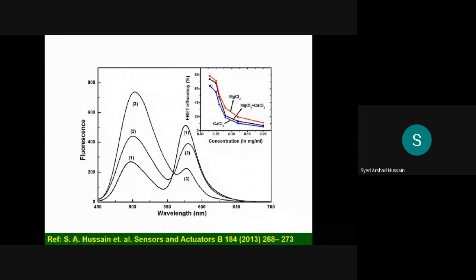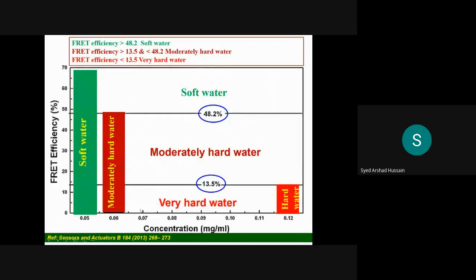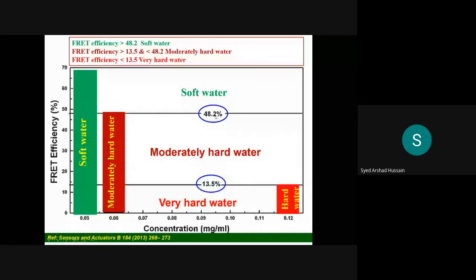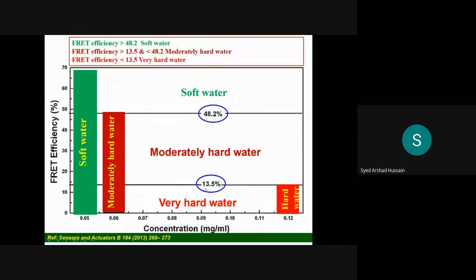So these are changes in intensity, efficiency, with the presence of magnesium, calcium or both ions. You see, almost linear. Then we analyze this, and based on the efficiency, we have this kind of plot. If the efficiency is, say, greater than 48%, then we say it's soft water. If the efficiency is between 13.5 and 48.2, we say it is moderately hard water. If it is less than 13.5, we say it is very hard water.